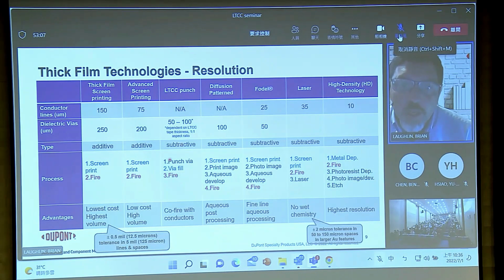200 micron size vias. And here, it's sort of a subtractive process from the dielectric standpoint, but additive from the metallization paste. And so there's just an extra process step of punching the via in the ceramic and then doing the via fill and fire. And this all is meant to co-fire with the other screen printing XY direction paste.